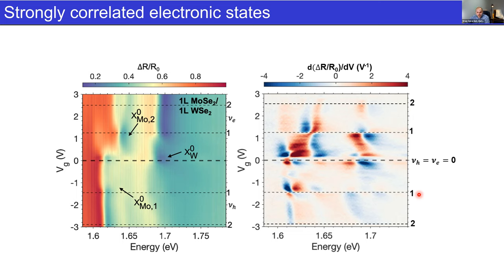But then we can start to add in additional lines. So we can see that there's additional modulations in this plot. And this corresponds to features at one-third and two-thirds, both on the electron and hole side. So you can see, for instance, this feature here stops and starts directly at two-thirds. The one-third, we have this feature started stopping here. And similarly, on the electron side.